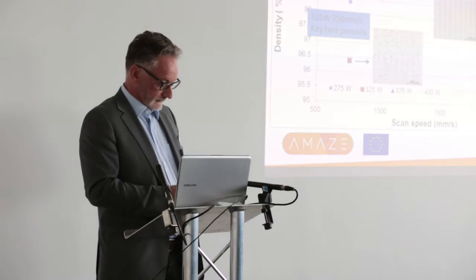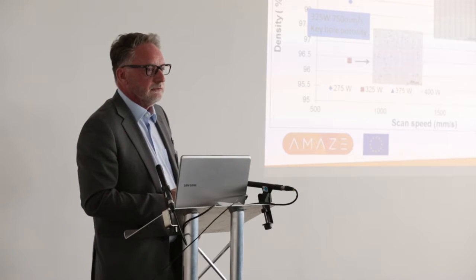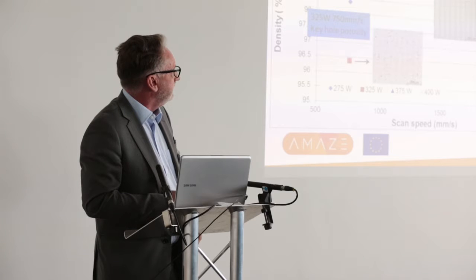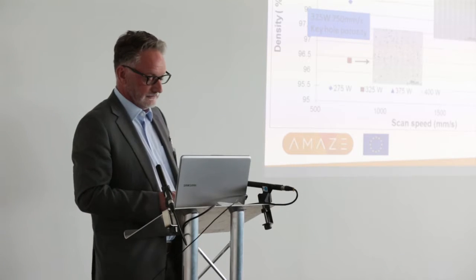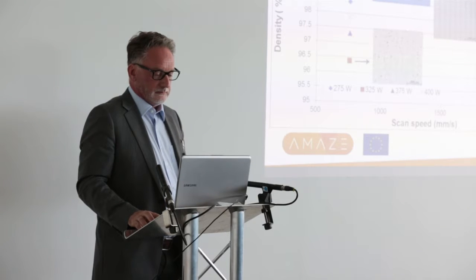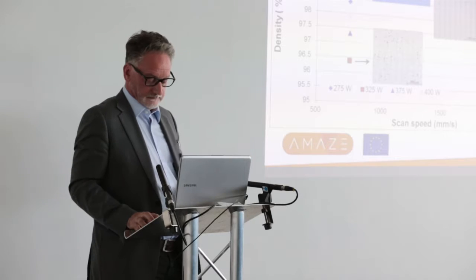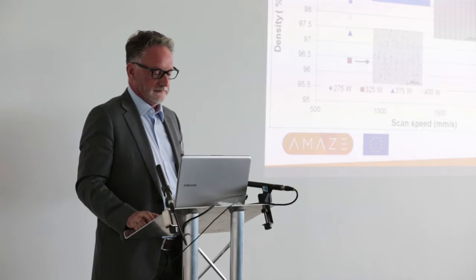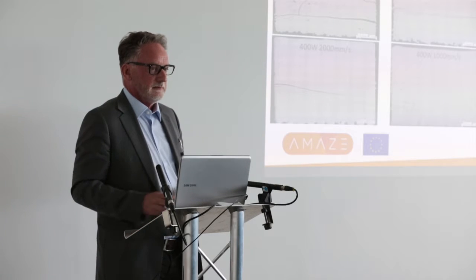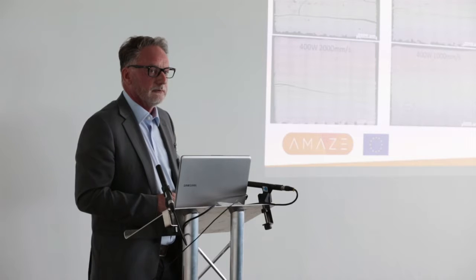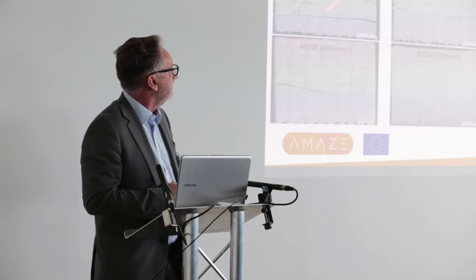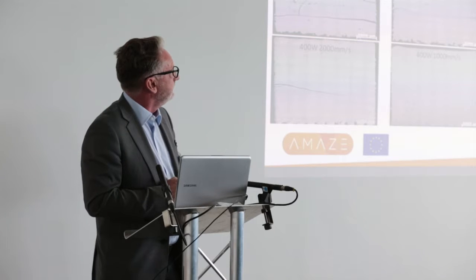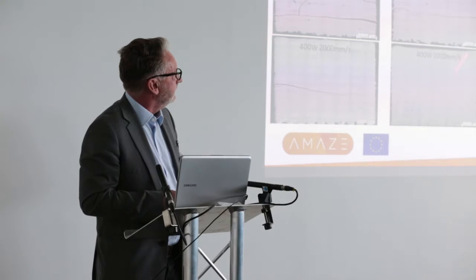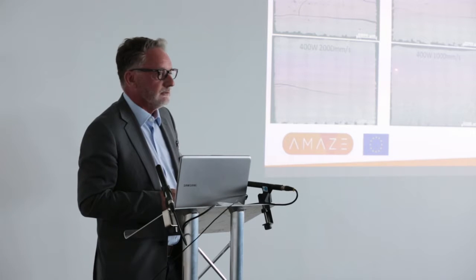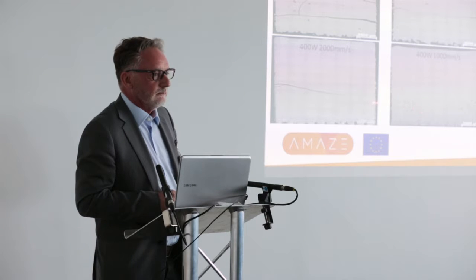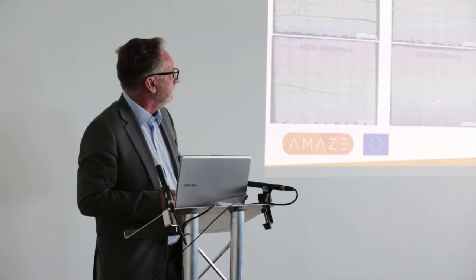Obviously you can overdo that, and if you went to too much power, with too slow a scan speed, then you start to get some keyholing porosity and some gas pores produced. So from that we were able to select the best conditions, which were 325 and 1500 millimeters per second. And then that was somewhat modified for some of the alloys because the other problem you get with the samples is that they would start to crack. So at the lower energy conditions, we're finding quite bad cracking. But as you decrease the scan speed and increase the laser power, then that will be overcome. So it was better to run the conditions with quite high energy towards the place where you're starting to get some gas porosity in order to avoid the cracking.